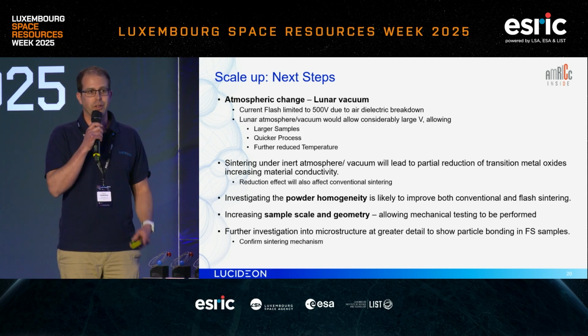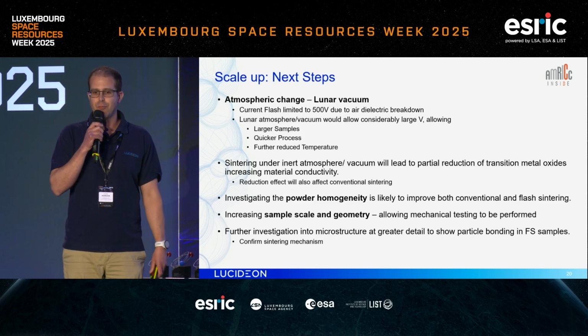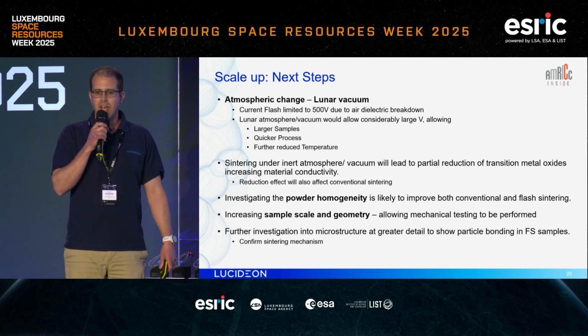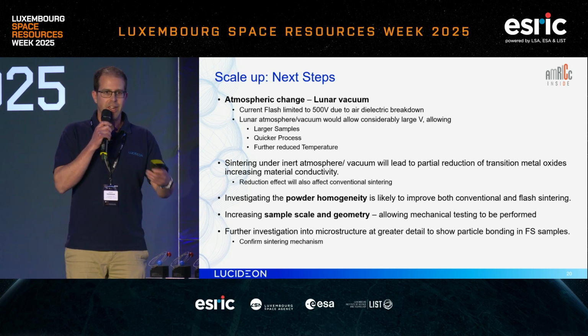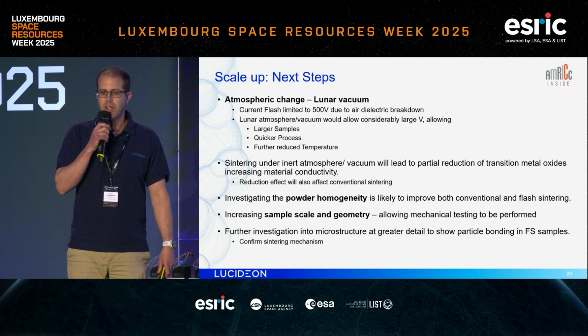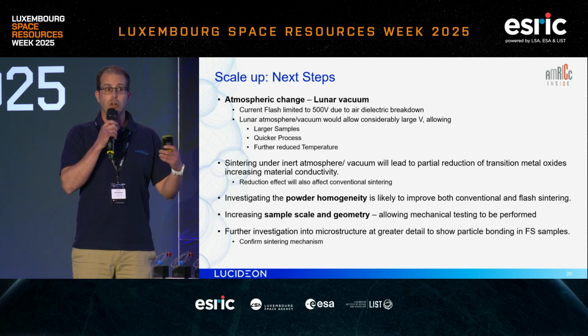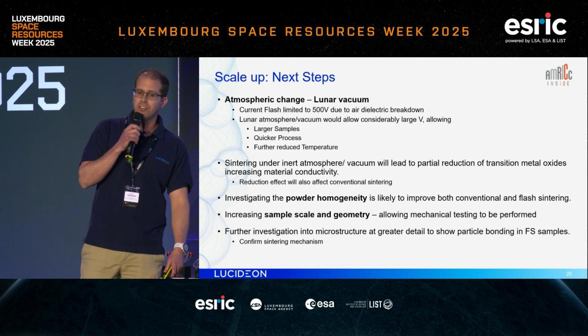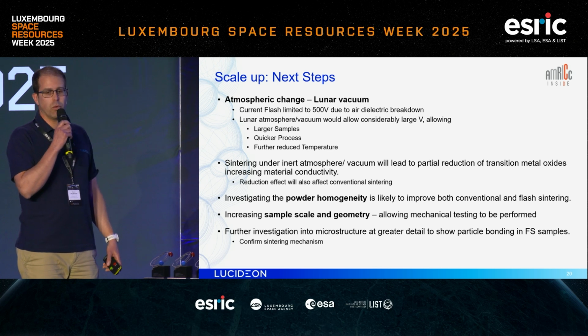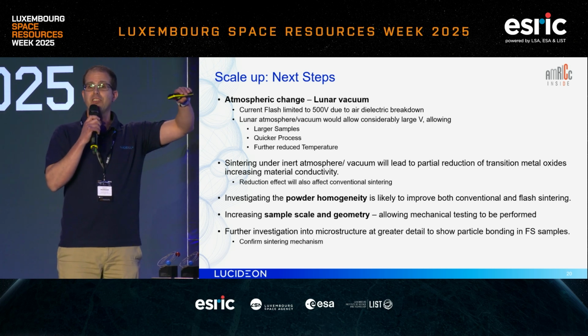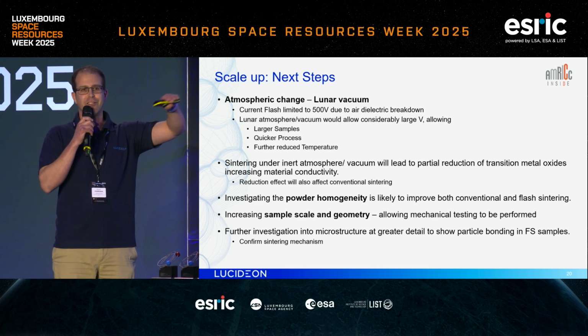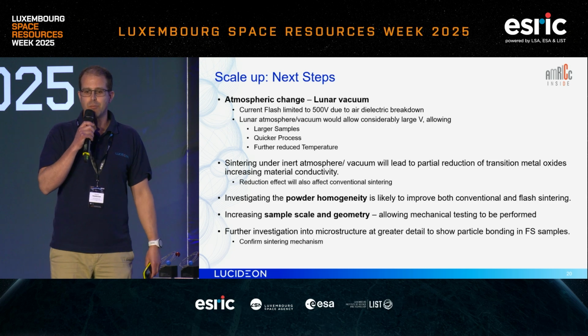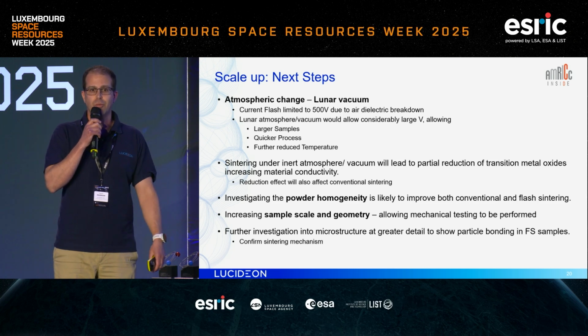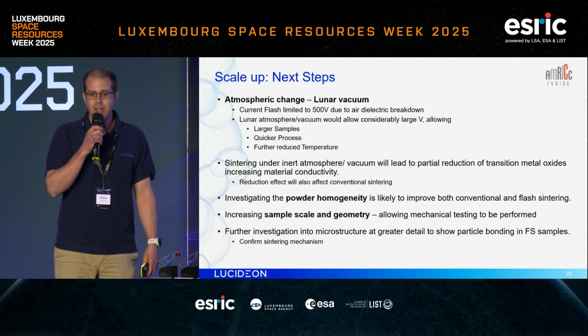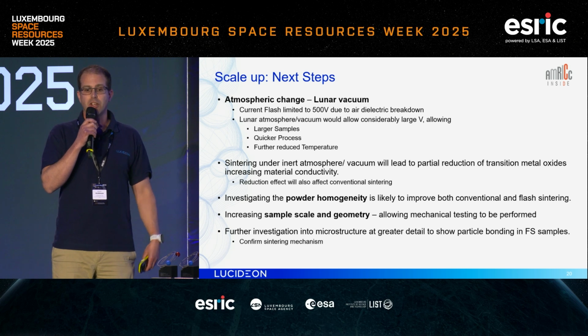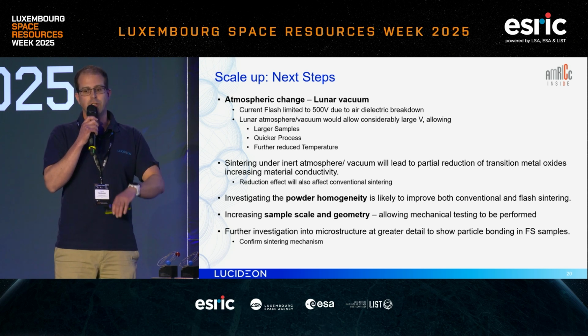We're really keen to get going and start making bigger samples, and of course getting into vacuum or a controlled atmosphere. This we feel would be potentially quite beneficial to the flash sintering process. It would allow less fireworks, or less ability for those localized melt systems, because the breakdown strength in a vacuum would be far greater. So we could potentially have larger samples and a quicker process with a further reduced temperature.